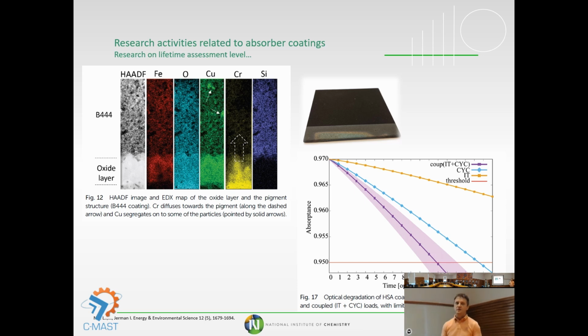So at the end, we realized that the most damaging process is really cycling because of expansion and then movements, thermal expansion, which influences the solar absorptivity at the end. As I said at the beginning, solar absorptivity was very important for them, just because they would like to have more than 95%. So we made a model, we put in the threshold, and we reached the number that those high solar absorptivity coatings will fulfill the demand of about 95% of solar absorptivity